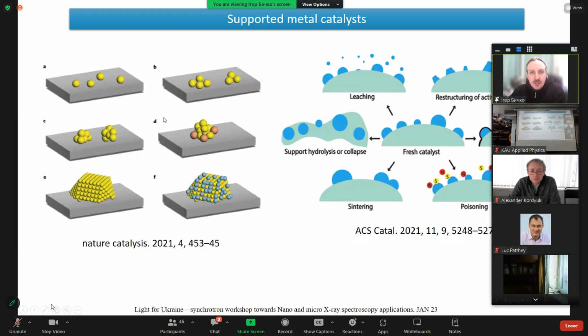Almost in all cases, catalysts represent atomically dispersed metals on the support. These are so-called single atom catalysts. It can be clusters of metals that contain 2, 3, 10, 20 atoms of metals. It can be small nanoparticles. It can be bimetallic or 3-metallic nanoparticles. And also it can be nanoparticles of different morphology, different form, and different phase structure. So as I said, it can be a particle where part of the particle is a metal, part of the particle is oxide, and another particle can be, for example, carbide. And the proportion of these phases depends on the reaction conditions. So we need to understand how it works.